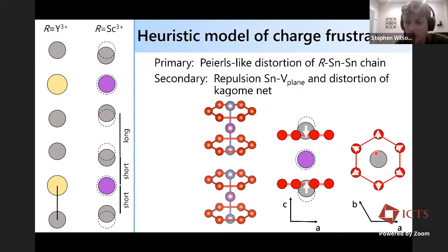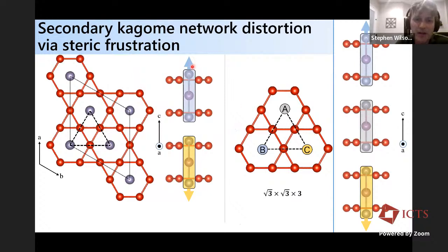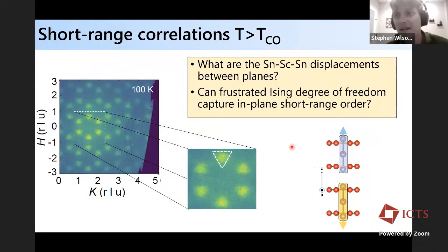So if you look at how you would tile that, if I can only move the trimer atoms up or down, which would correspond to the third, a third, a half wave vector, then it's frustrated in the plane. If I just think about this Ising degree of freedom, I can't tile this triangular lattice with up and down without frustration. But instead, the system in the charge ordered phase switches, and along the chain, one trimer moves up, one trimer moves down, and one doesn't move at all. So then you can tile the triangular lattice in a three-state, Potts type of tiling. That's the idea of how you could have lattice or steric frustration in the system.